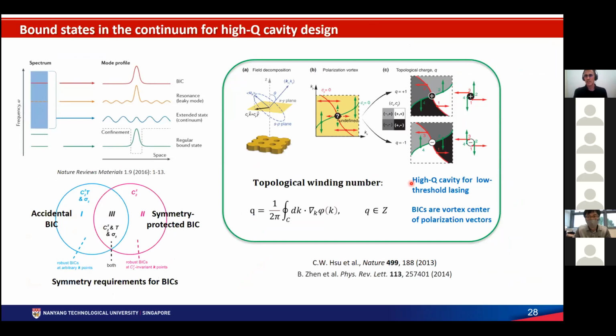And the reason is that bound states in the continuum are very high, almost theoretically infinite Q factor resonances that are actually happening in the continuum, the bound state that appears in the continuum. And when you have an emission, for example, they will appear as intensity minima at the center of polarization vortex laser beams. And if you follow the polarization across the vortex and count how many times the polarization winds while you complete a full circle around it, you can determine the topological winding number of your polarization. That is supposed to be an integer.